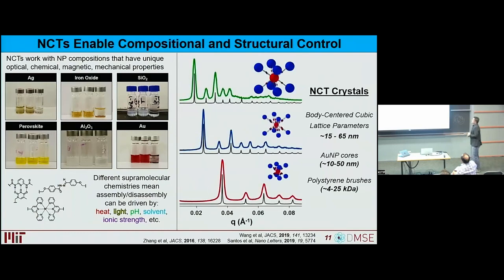If we take these assemblies, we heat them above their melting transition, and we slowly cool them down, they will indeed form ordered lattices. So these are some of the first lattices we made with NCTs. Each of these is a body-centered cubic type lattice. The color traces here are the actual SAXS patterns of the material. The black traces underneath are the predicted scattering patterns for a BCC lattice, and you can see they match very well. Each of these unit cells are drawn to scale to give you a sense of where we started in terms of the size of particles and the lengths of the polymers we can work with. We've now since expanded outwards from that, and I'll give some examples of that as we go through today.